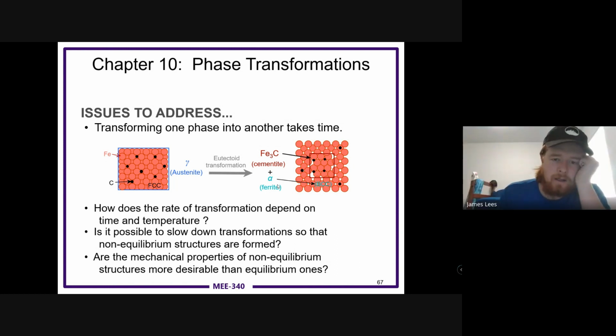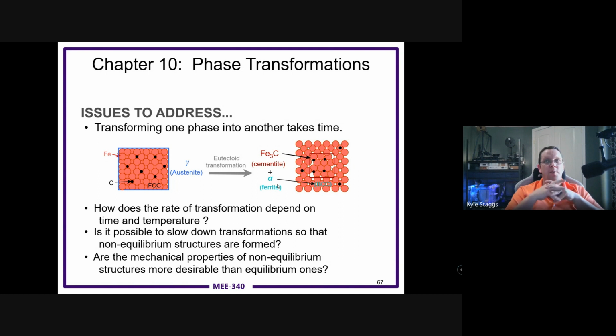If you're not in equilibrium, does that mean that the properties are going to change while you're using the material? It means the properties are going to change throughout the material, just like this example where you have ferrite here and you have cementite here, right? So one of these is hard, one of these is soft. If you imagine a cutting bit physically running through these, the cementite is going to catch the bit and cause friction, or the cementite's going to catch the bit and cause friction. The ferrite is just going to sort of melt like butter against a cutting tool, right? And so in the case of something like machining, you have unevenness in the material, and that can screw around with your tolerances if you're machining in a way that's, hey, only spend a few seconds on this path. You're making some assumptions about the behavior of the material under the cutting bit, but if your hardness throughout the material is going up and down, that could be bad, right?